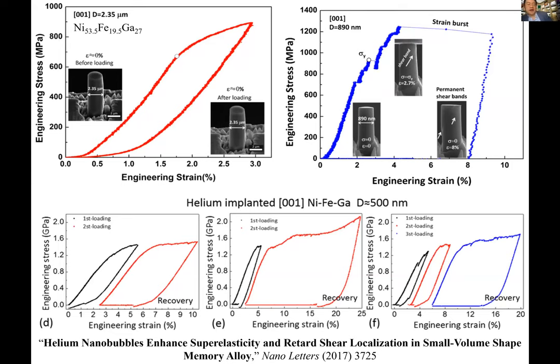This also has an effect on the shape memory or superelasticity effect. For example, take this nickel-iron-gallium system, a well-known superelastic material. It means that when you compress it and then unload it, it completely goes back. Even though there's energy dissipation, there is no plastic strain when you unload. But there is a size effect. When we go from 2 microns to about 1 micron, the superelasticity is completely gone. It becomes plastic, so no more phase-transformation-induced superelasticity.